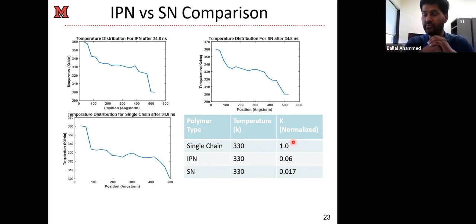When you think about heat transport, we think in terms of phonons. In a single chain, when a phonon propagates, it is less scattered because it doesn't have any crosslinkers or any other stuff. So the phonon can propagate easily in those materials because there is no aperiodicity in this one single chain. That's why we have a larger thermal conductivity, almost 2 orders of magnitude more than the IPN and SN. For the IPN case, as you remember, it allows more bond formations. When you have more bonds in the IPN, that means more routes for the heat to transport. As a result, I think the thermal conductivity increases.